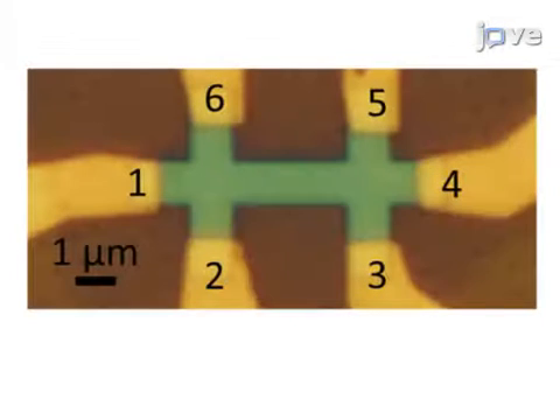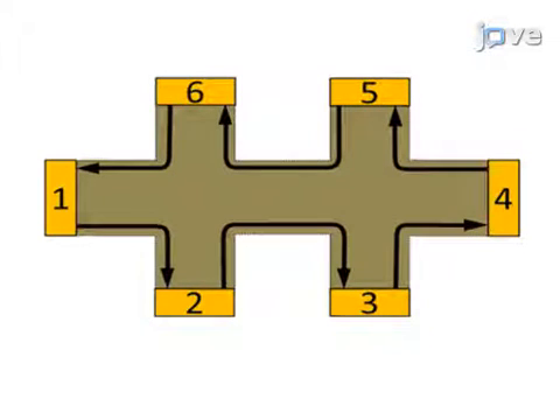A Hall bar device was patterned in graphene stacked on hexagonal boron nitride for a low-temperature magnetotransport experiment as described. This schematic shows the Landauer-Büttiker edge states that arise from the Landau levels. These edge states provide a transport mechanism to calculate the values of measured Hall resistances.